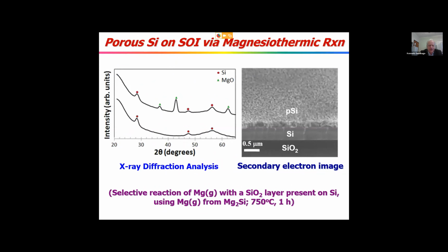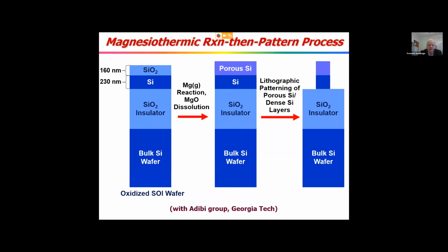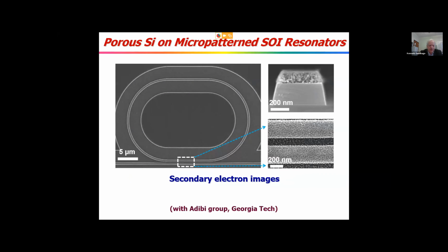And you can see on the right the very nice conformal, uniform thickness, highly porous silicon layer we put on silicon. So then the Adibi group patterned this lithographically. Here's a top-down view showing the racetrack and the nearby linear waveguide. If you zoom in, you can see a cross-section of porous silicon on top of the dense silicon that we made, and the top-down view of the waveguide and the resonator.